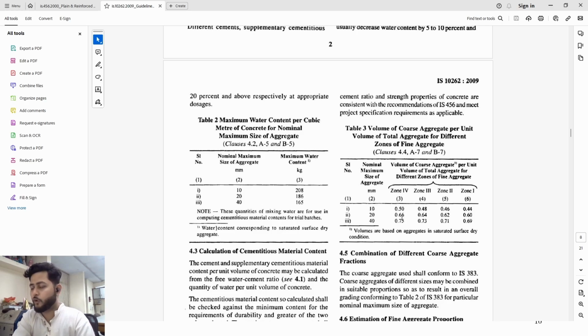Now once you calculate the volume of total aggregate, and from this value of coarse aggregate to total aggregate ratio, let's say 0.64 or something, you'll be able to calculate the volume of coarse aggregate and the volume of fine aggregate in the total aggregate mix. Since you know the specific gravities of both types of aggregates, you'll be able to calculate the weight content of each of the aggregate types. This is the generic procedure to proceed once you have decided on the water content and the cement content in the mix, to calculate all other weight proportions in the concrete mixture.